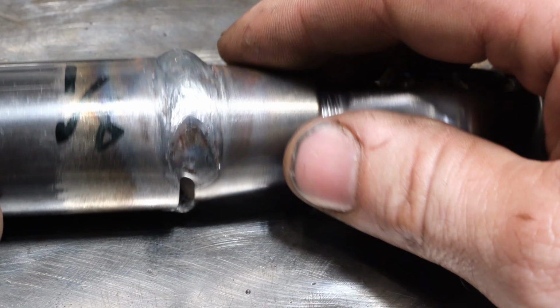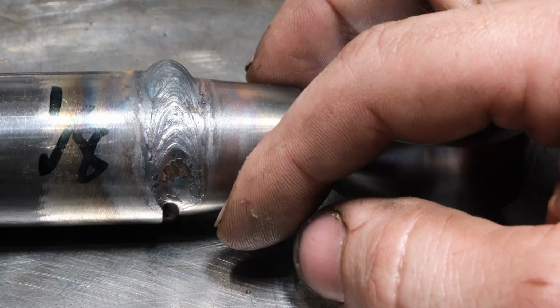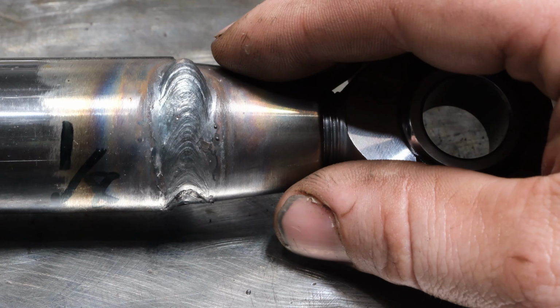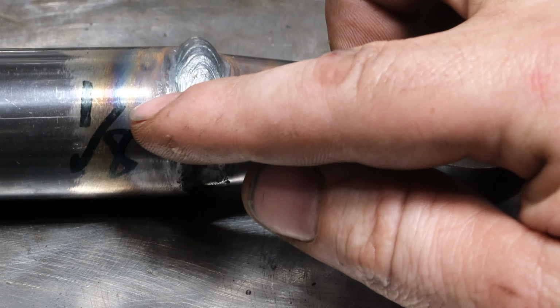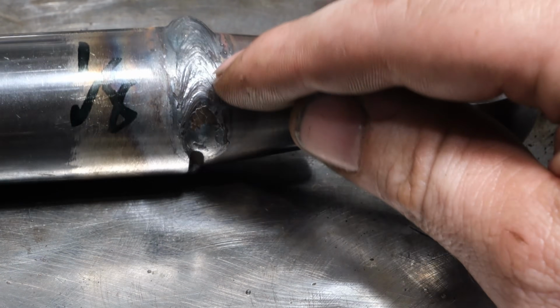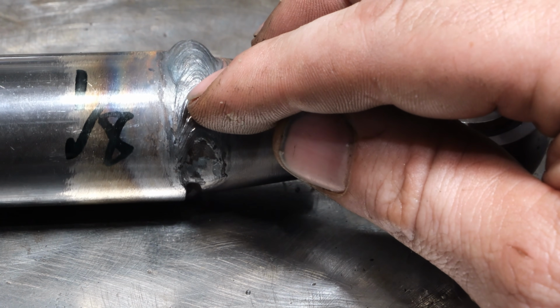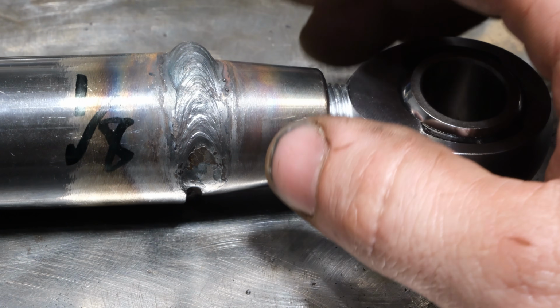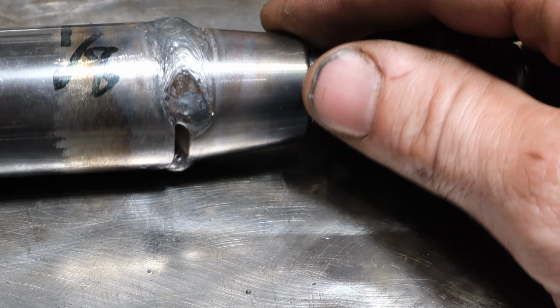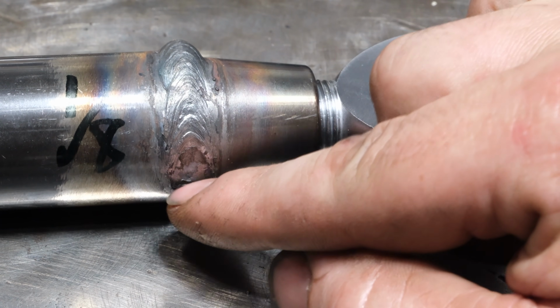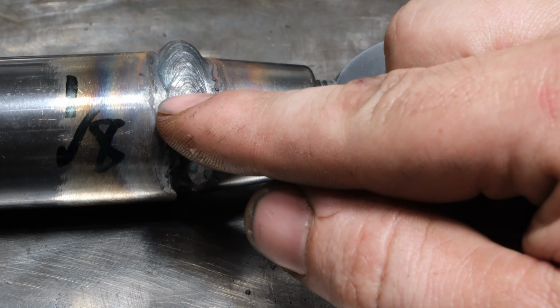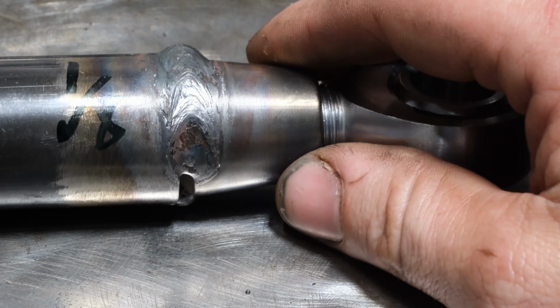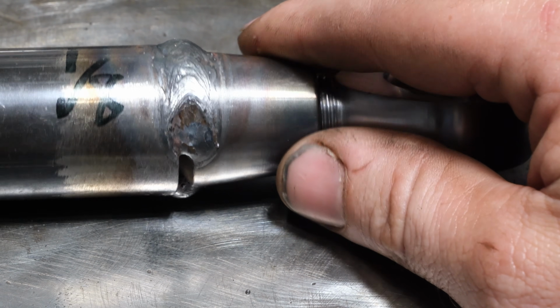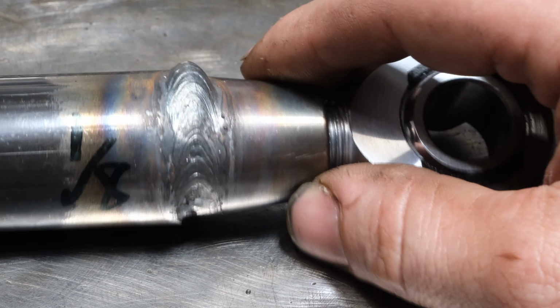Little bit hot here. Now, one of the things I kind of screwed up on, again, I don't stick weld stuff like this very often. Well, I've never done anything like this with stick, but small, thin tube. I ran about 130 amps on this, which is normally what I weld 3/16 plate with an 1/8 inch rod. Well, that was a little bit hot because of the gap and the amount of metal I had to fill in there. So I would definitely say 115 to 120 would be far better on this. It would give you more control.